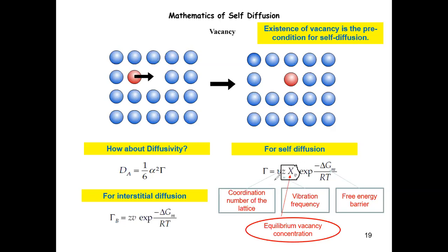So it's not only a function of the coordination number, which is Z. You have to take the coordination number and multiply by the vacancy concentration. So this gives you, out of this Z number of neighbors, how many neighbors on average are going to be an empty site that I can hop into. And this XV is the vacancy concentration, which is the probability that a randomly selected position or atomic site is a vacancy site. Does this make sense to everyone based on our analysis?